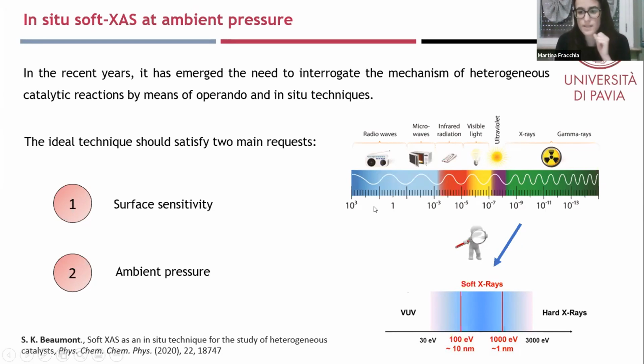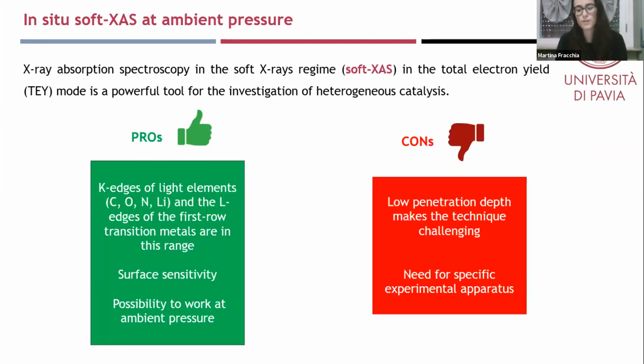These X-rays have an energy which is lower than 1000 electron volts. So they have a very low penetration depth, and usually they have been used for surface science experiments and under high vacuum. However, it's also possible to acquire operando X-ray absorption spectroscopy with soft X-rays at ambient pressure, using total electron yield as the acquisition mode.